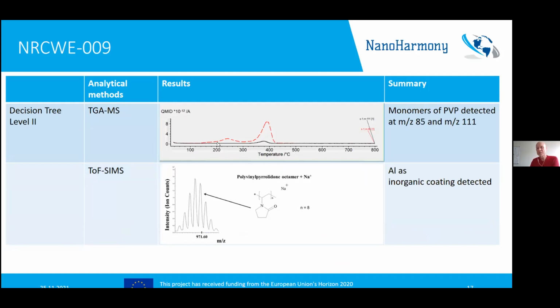how if we use TGA-MS in an inert atmosphere, we can see that we come up with a fragmentation pattern which can be compared with normal MS library results. So by looking at the fragments at m/z 85 and 111, we actually identify the structure of the monomer in the organic polymer. So TGA not only measures the overall mass loss. In this case, it actually also identifies the structure of the organic polymer.